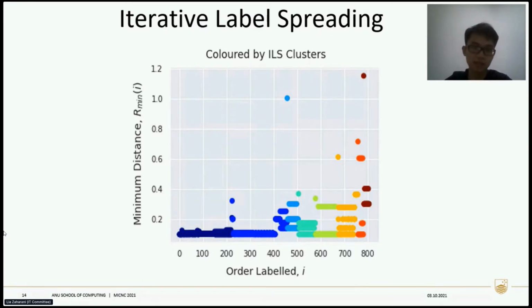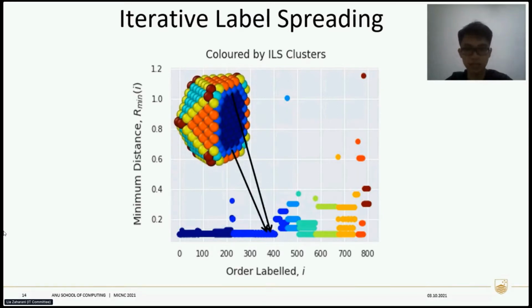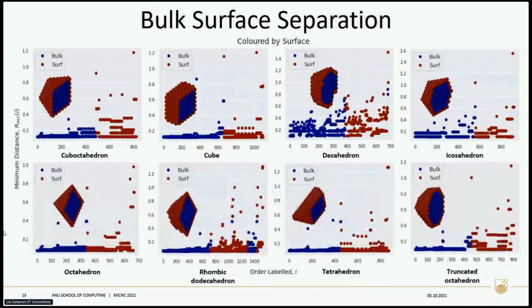Now note that I've said feature space and not Cartesian coordinate space. So the atoms on the opposite sides of the nanoparticle could still appear very close together in the ILS distance plots. Here are the results of the ILS distance plots for nanoparticles with different shapes, which I colored by whether the atoms belong to the surface layer. Looking at the ILS distance plots, we can see that it's possible to achieve satisfactory separation between bulk and surface atoms, as long as we can find the highest peaks in the middle. The only exceptions are decahedron and rhombic dodecahedron, where some bulk atoms are mixed within the surface atoms cluster.